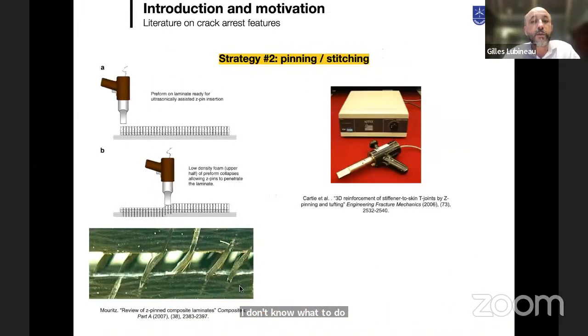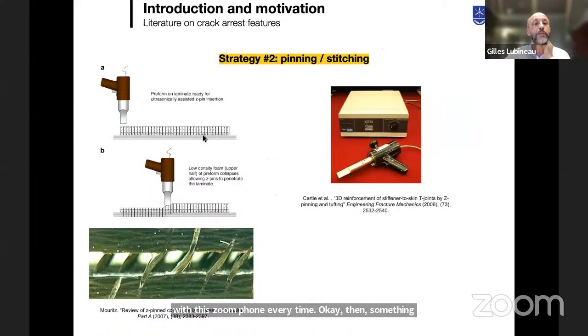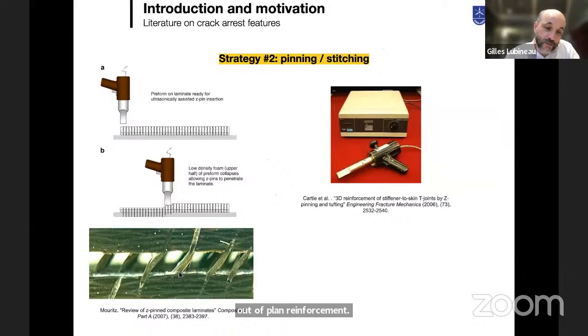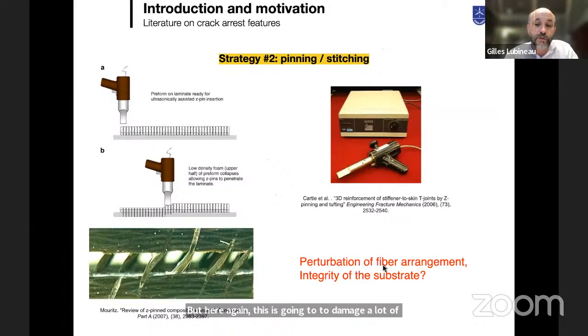Then something that you know very well in composite engineering is what you call Z pinning. That means you are going to come with pins that you will introduce within the substrate by using an ultrasonic gun. So this is something that will result in out-of-plane reinforcement. But here again, this is going to damage the substrate a lot, because you know that this introduces a lot of perturbation of fibers, and there are real questions about the integrity of the substrate.